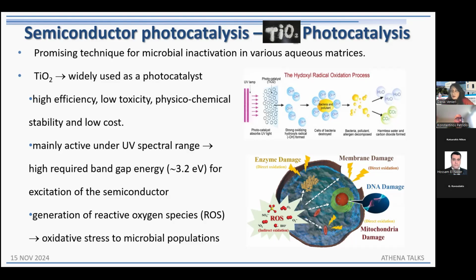Now, what's going on with titanium dioxide? It is mainly active under the UV spectral range with a high required gap energy, as you may see here, approximately 3.2 eV, for excitation of the semiconductor. So upon illumination, what happens is the generation of reactive oxygen species, the so-called ROS, which ultimately cause oxidative stress to many different microbial populations.